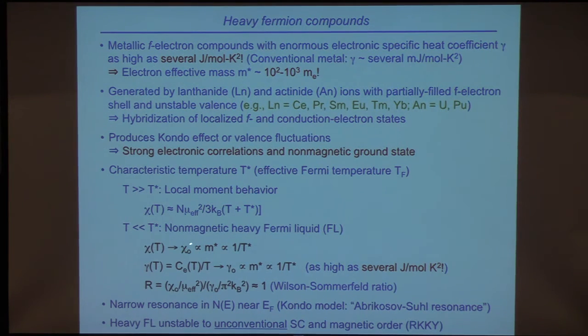And so the susceptibility will approach a constant value proportional to the effective mass and proportional to 1 over the effective Fermi temperature. Similarly, the electronic specific heat coefficient, gamma, will become constant, proportional to m star and 1 over T star. Again, this can be as large as several joules per mole Kelvin squared. And this ratio, called the Wilson-Sommerfeld ratio, is of the order of 1, and it tells you that you're dealing with heavy itinerant electrons. You also get a narrow resonance in the density of states near the Fermi level. In the Kondo model, it's called the Kondo resonance or the Abrikosov-Suhl resonance. And this heavy Fermi liquid is unstable to some very interesting types of unconventional superconductivity, which I won't be saying much about, and then magnetic order via the RKKY interaction.